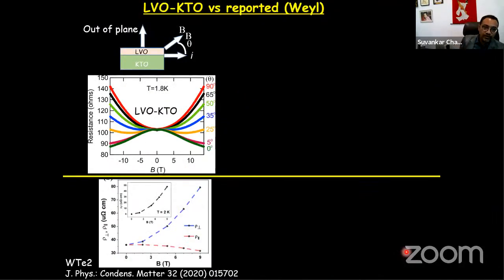So now let me give you a comparison of our sample with a known topological material. Please note now the definition of theta has been changed from here to here. So now theta equals 0 is I parallel B. So you can see for our material, I parallel B has a negative magnetoresistance and I perpendicular B, which is out of plane, has a positive magnetoresistance. This is the out of plane measurement. And in a well-known Weyl material, the situation is very similar: when you apply the field in the direction of current, you have negative magnetoresistance, and perpendicular to that, out of plane, is positive magnetoresistance.